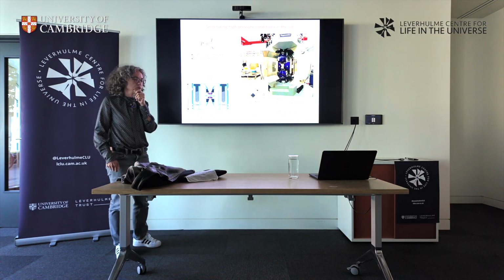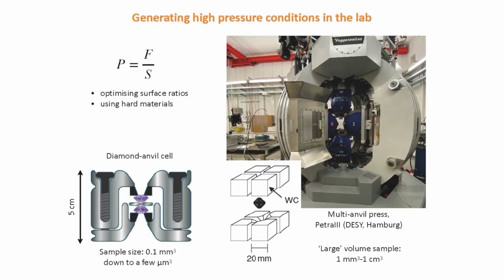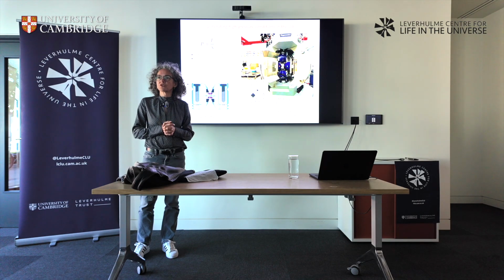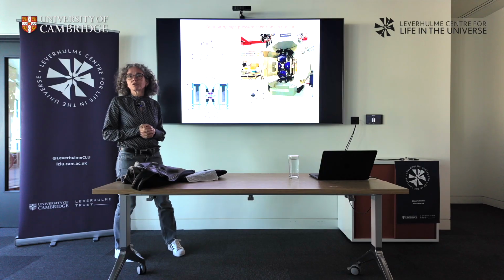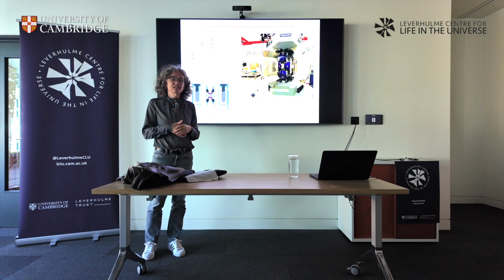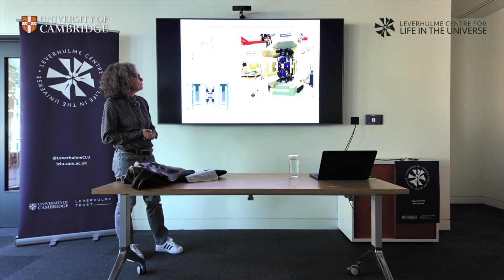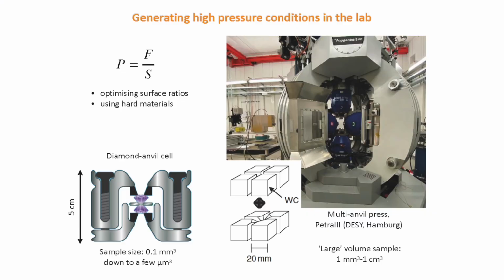There is only one way to reproduce high pressure: put as strong a force as you can on as small a surface as possible, to optimize the force-surface ratio. You also need to work with very hard materials so that the force is transmitted as much as possible. There are two types of experiments we've been doing, which we qualify in terms of sample size. If the sample size is 1 cubic millimeter, we call it large volume, and for this we use multi-anvil presses.